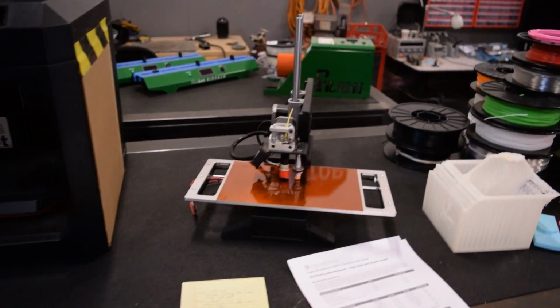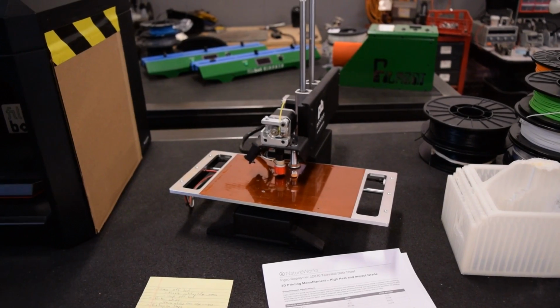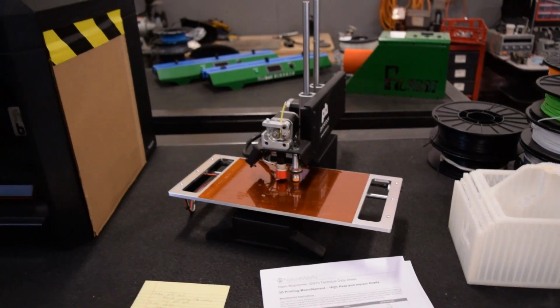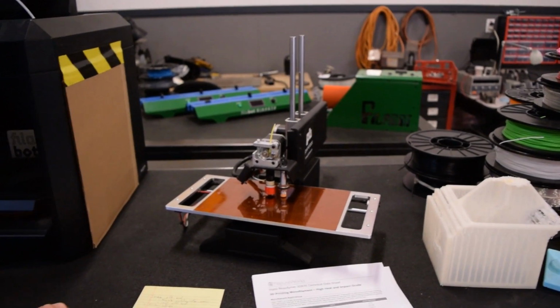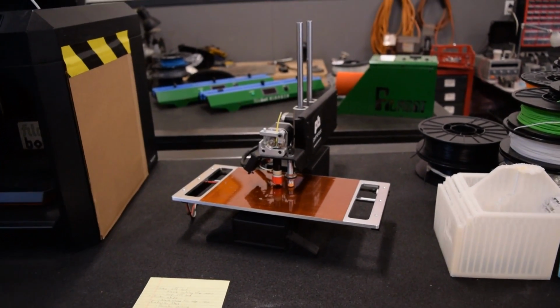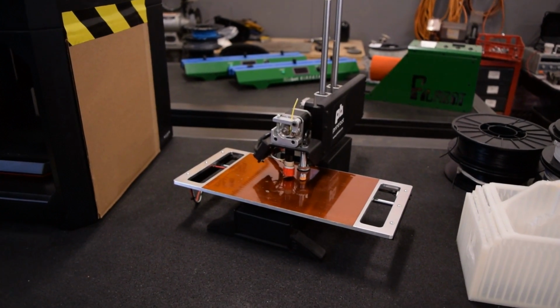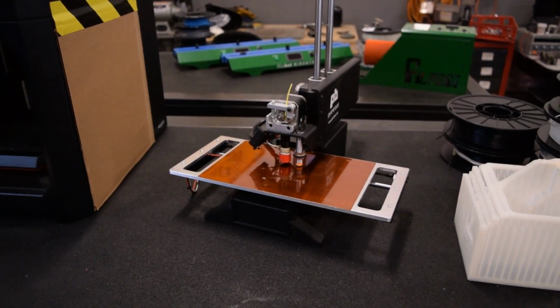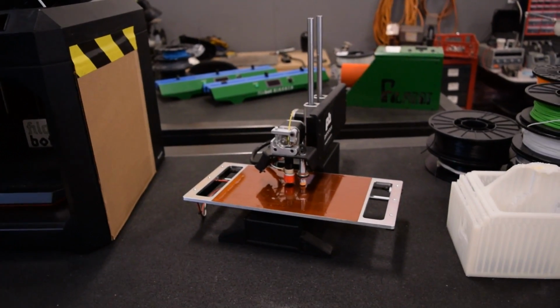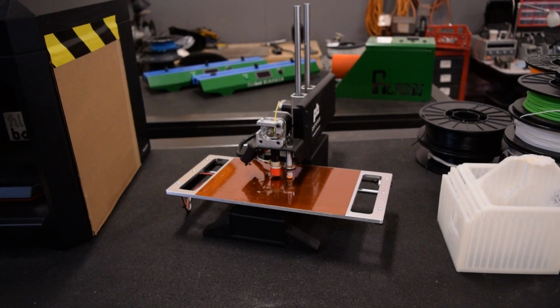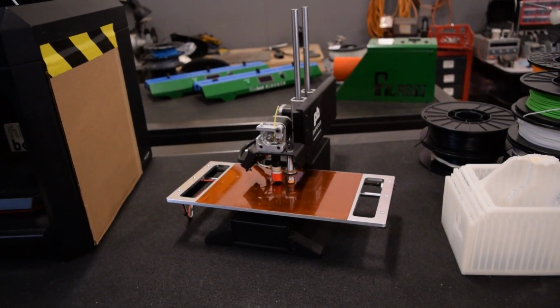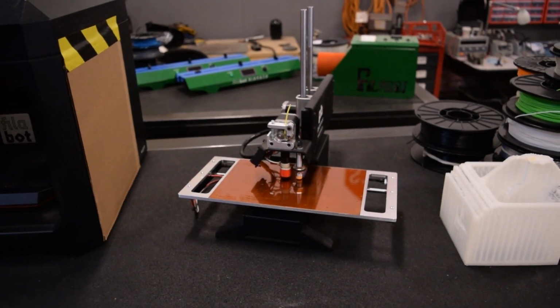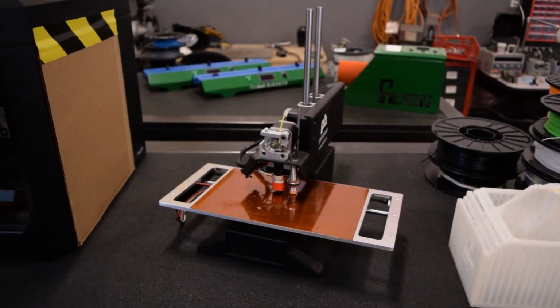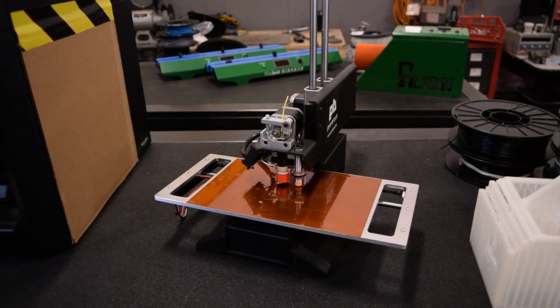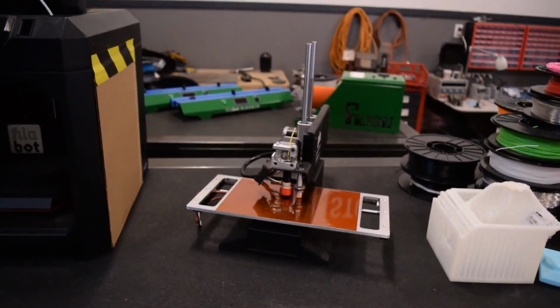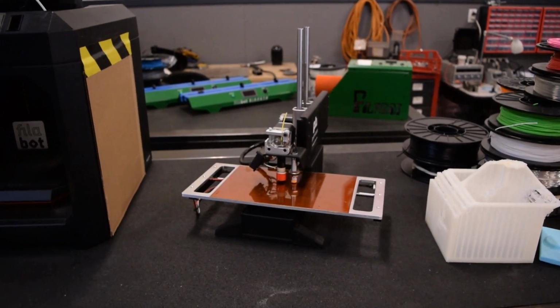That's one of the other things, bed heat and cooling. That's a way of controlling the environment around your print. If you can reduce the temperature difference between the melt temp of the polymer and the solid state of the polymer, you can keep it from shrinking so much. If you have the part all at one high temperature while you're printing, and then you cool it all at once, then the print will be successful because you won't have it warping as it's printing. In most open air printers, it's cooling down to room temperature as it's printing. So that's a high temperature differential, which makes for the worst warping.